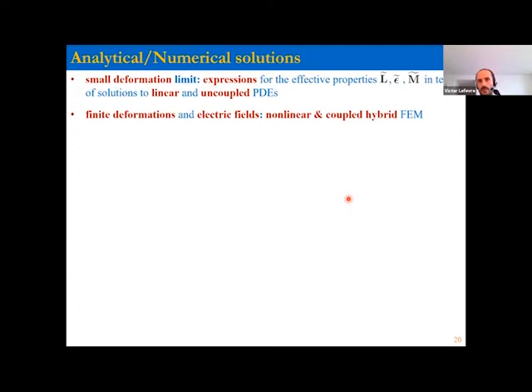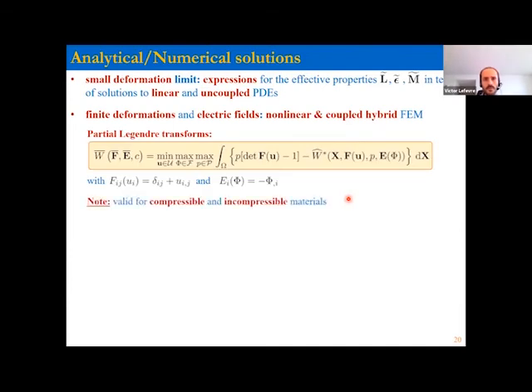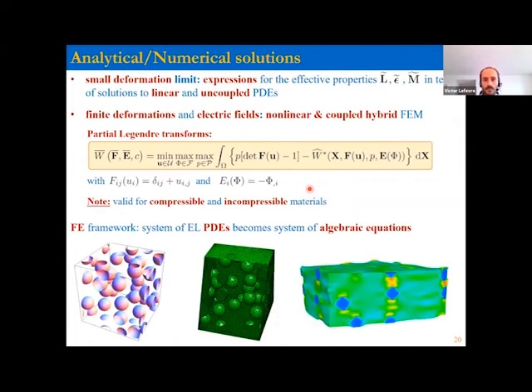And so what we did was to implement a nonlinear and coupled hybrid finite element framework to do that. So what we did was to use partial Legendre transforms to account for the fact that these are incompressible materials. So in doing so, we introduce another field, a pressure scalar field that's associated with the incompressibility constraint, in addition to the displacement field and the electric potential. And so then it's just a matter of using the finite element framework and to convert the system of Euler-Lagrange PDEs associated with this variational problem into systems of algebraic equations that the computer can solve for you.